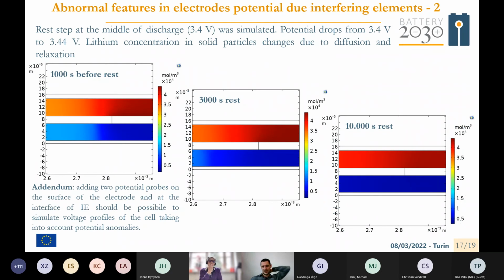As you can see here, we performed the last test with the model, where we simulated the behavior of the lithium concentration in solid phase in the cell during a discharge part of the curve. And then we introduced a rest period, where we simulated applying zero current basically to the cell, and in this period the distribution of lithium in solid phase at different times was evaluated.